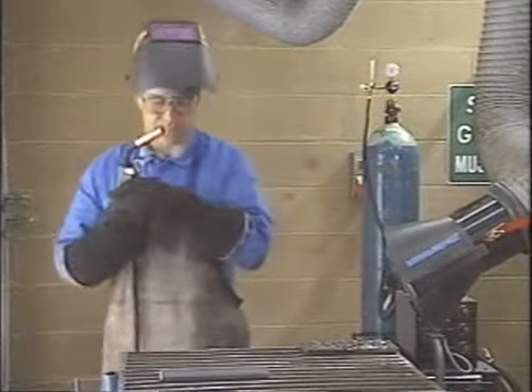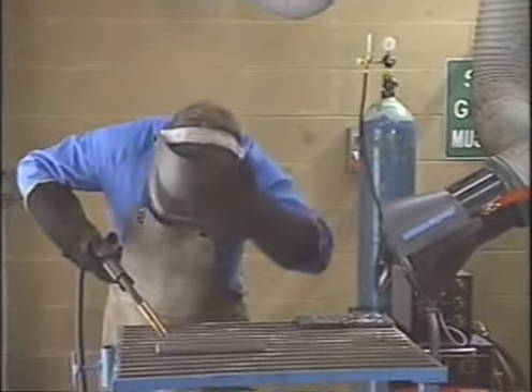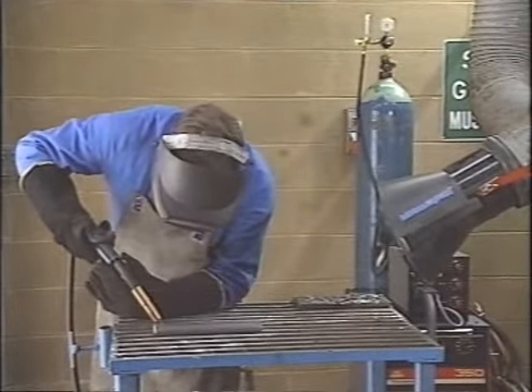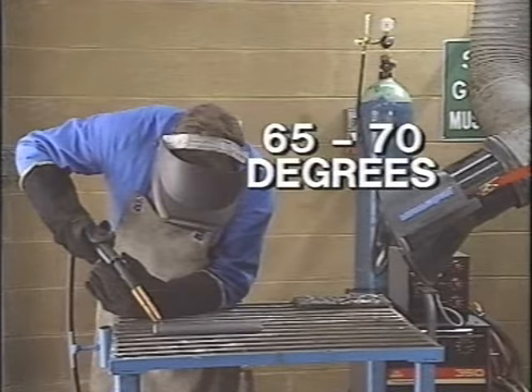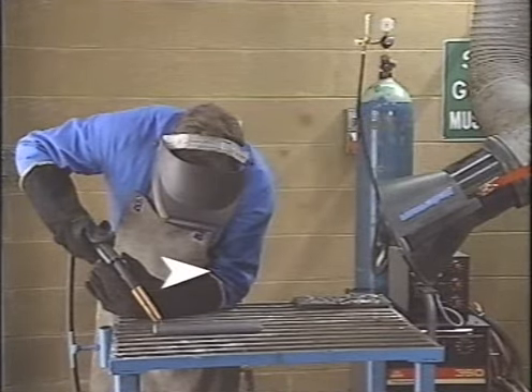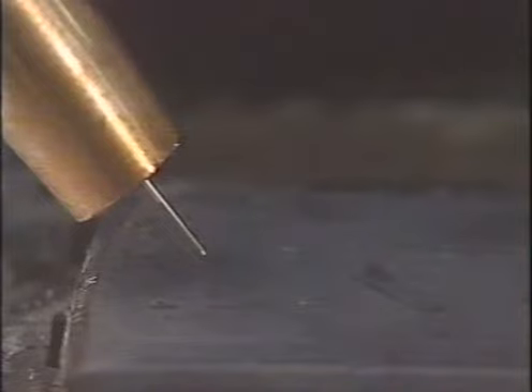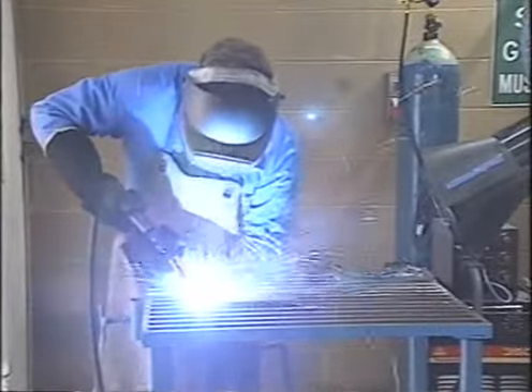First of all, make sure you have your shield or helmet in position. Holding the welding gun at an angle of 65 to 70 degrees in the intended direction of welding, with the nozzle approximately 10 millimetres away from the workpiece, depress the trigger. The wire and gas will flow and the arc will be established.